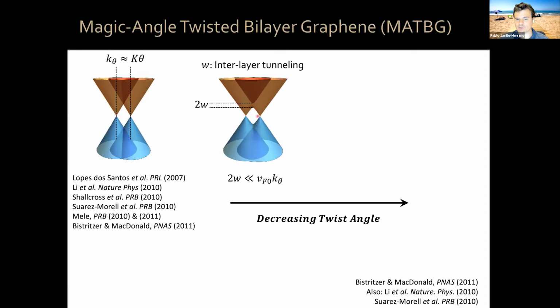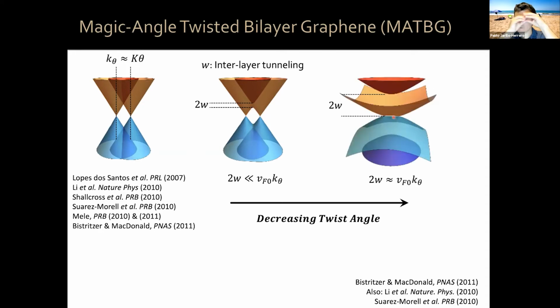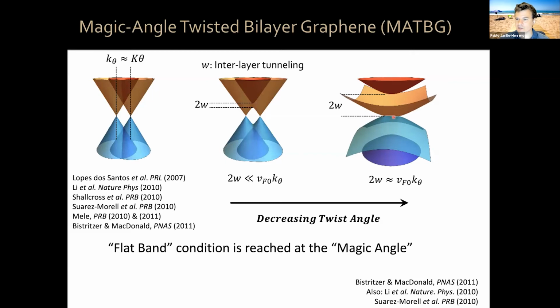So this band gets pushed down and down to lower and lower energies until it gets pushed down flat to 0, okay? At that instant, we say that a flat band condition has been reached, and it's reached at the magic angle, which happens to be, for graphene on top of graphene, 1.1 degrees. It depends on that interlayer tunneling.